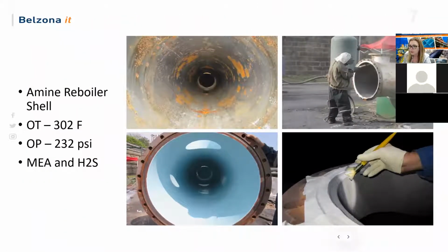Another area we can help out with would be lining reboiler shells like you see here. This is the inside of a reboiler at a natural gas plant. The equipment was suffering from severe pitting and wall thinning due to exposure to H2S and MEA at 302 degrees Fahrenheit. You can see the next picture over shows the vessel being abrasive blasted in preparation for the coating. And we did this on site with their local contractor.